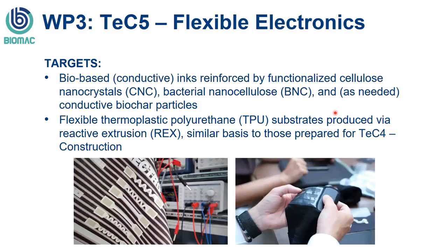And then finally, test case 5, flexible electronics. Here, the target is twofold. First, a series of inks, because we're talking about printed flexible electronics. You can see some pictures here. So what you should have in your mind is you have a base layer, which is a flexible material. And on that base layer, that flexible material that is relatively low melting, let's say, you're printing a variety of devices. And you're doing that using a conductive ink and using a non-conductive ink.